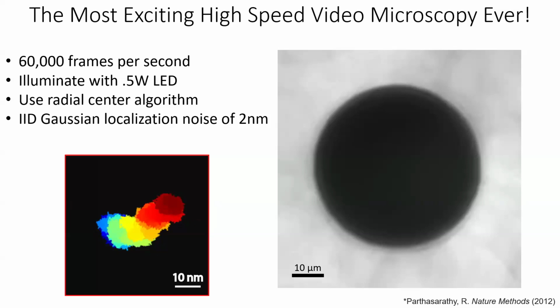And so with this 50 micron particle, the bigger the particle that we use, the more that it's moving. So our goal was to essentially get the biggest particle that we could use that would fit within the confines of our zoomed in high-speed camera and would have the right optical properties and sedimentation properties, etc. So the point is that we can measure this one particle extremely well.